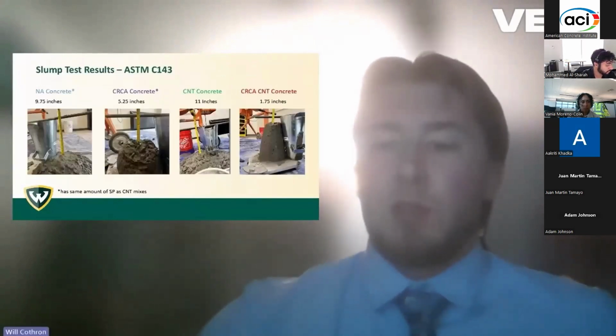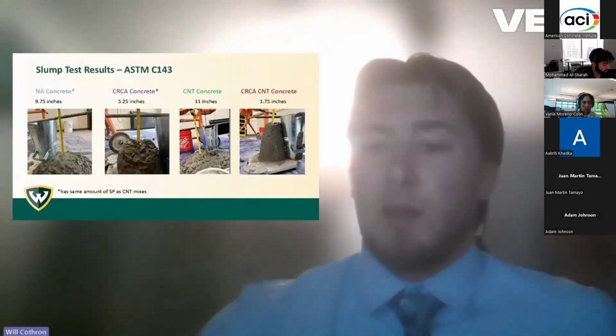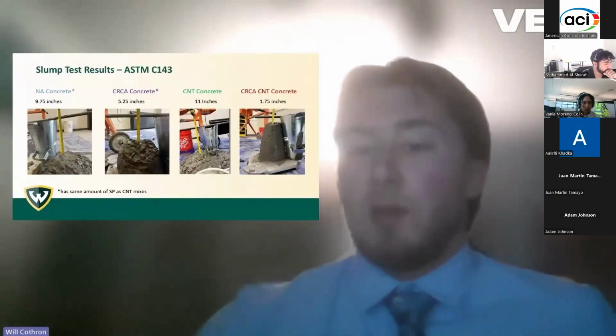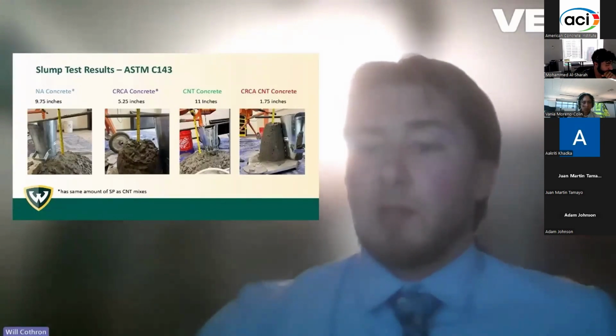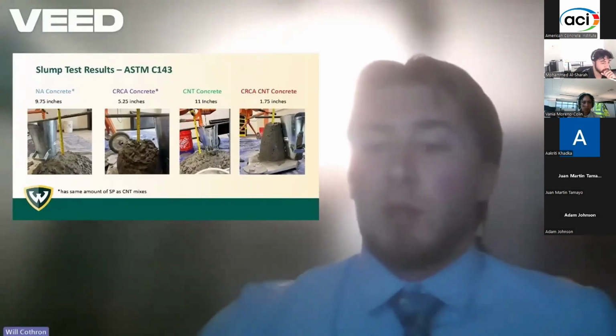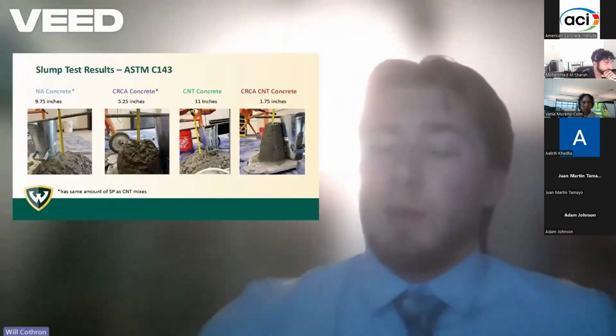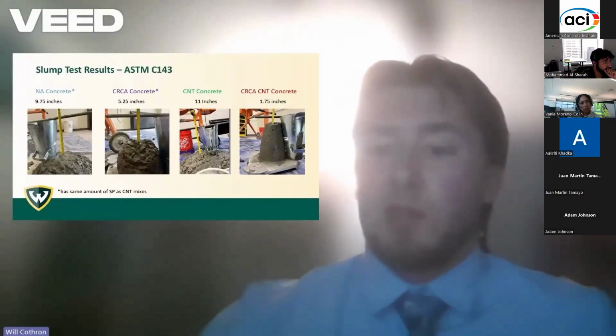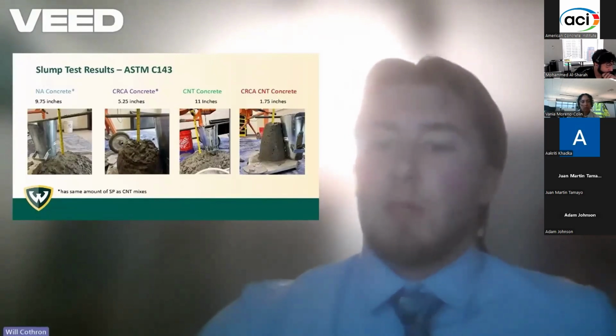To understand how carbonation treatment and carbon nanotubes affect the fresh properties of concrete, we performed slump tests following ASTM C143. The natural aggregate concrete exhibited a slump of 9.75 inches, indicating good workability, typical of conventional concrete mixes. After carbonation, the slump decreased to 5.25 inches. This reduction in slump corresponds to the decreased water absorption. We previously observed through the TGA and water absorption tests that we have a denser aggregate surface after carbonation.